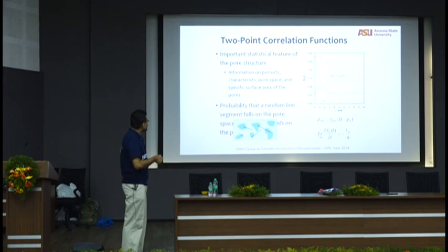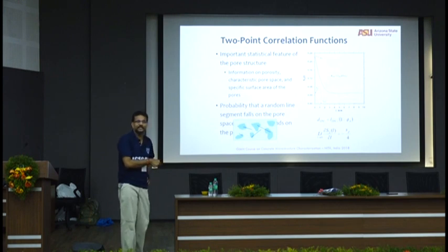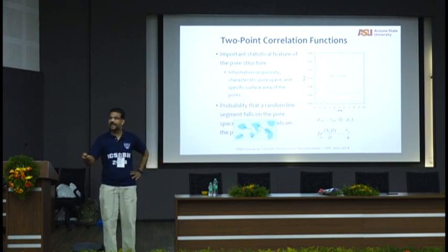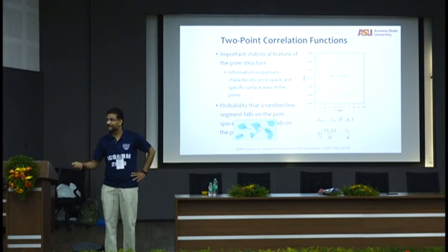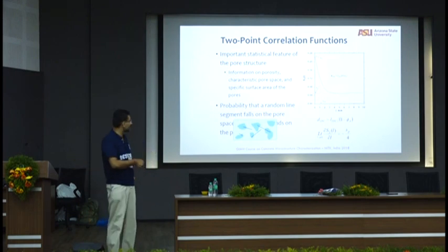And if I draw a tangent to the line at the initial point, and look at where it intersects the horizontal, the intersection of the tangent and the horizontal, which is this point, I can use that point, a critical length, along with the porosity to find a critical size of that phase. That critical size, again, is related to the percolation size. Okay, so now you have another tool.